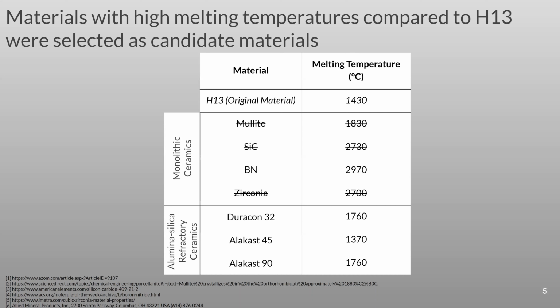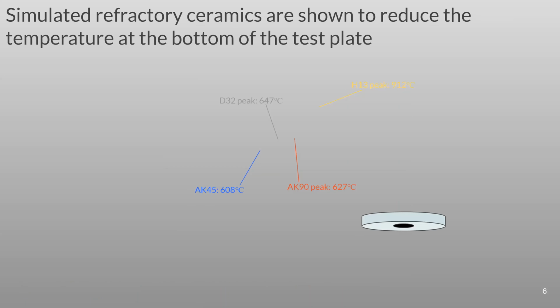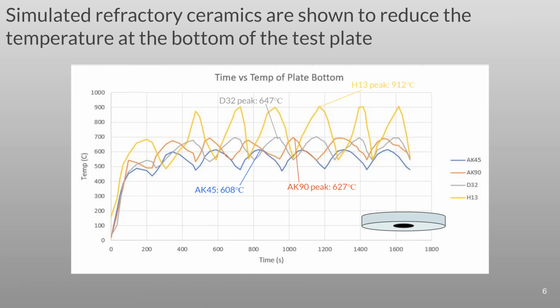Thermal shock resistance was evaluated for H13 and 4 monolithic ceramics. Of the 4, boron nitride was the only material that survived thermal shock. 3 refractory ceramics were also selected for testing. Simulations were conducted to analyze temperature at the bottom of a test plate that would be in direct contact with the shot sleeve. The pour cycle that reached the highest temperature for each material is labeled below.